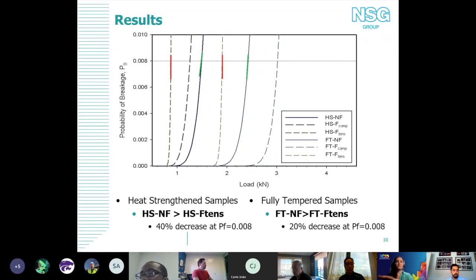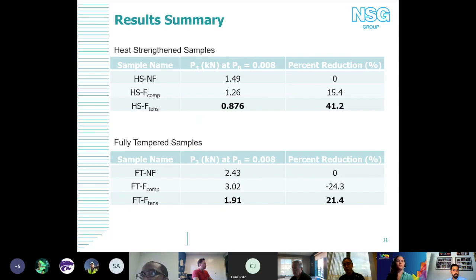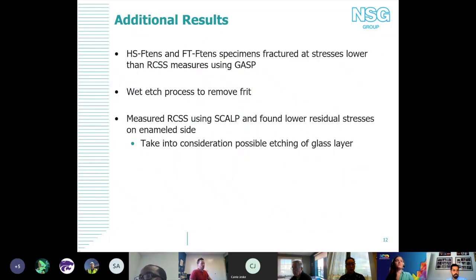Next slide. This is just a quick layout of what those percent reductions look like. We can move forward. Whenever we realized that the glass was fracturing at stresses lower than the measured RCSS, we did use a wet etch process to remove the frit and try to measure what those residual compressive surface stresses were, and we found them to be significantly lower than what is actually defined as heat strengthened or fully tempered by ASTM.